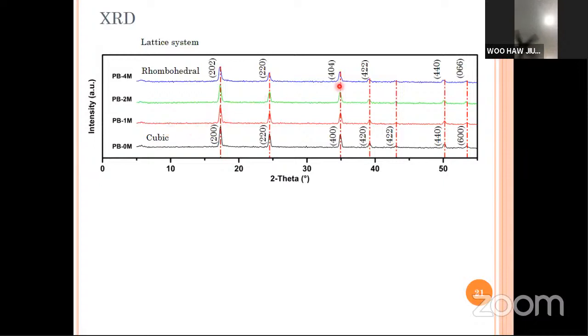What we observe is we are still getting all the peaks, but with a slight shift to the left. And as we run the matching, we found that instead of cubic structure, now it turned to rhombohedra. So the lattice system has changed slowly from cubic to rhombohedra.